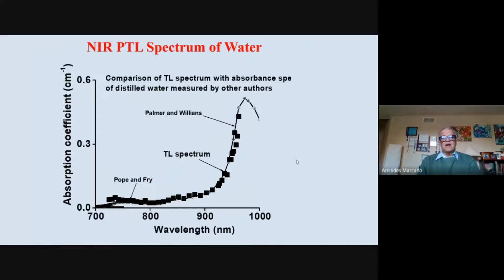You can also do a similar experiment using, for example, a femtosecond laser, what they call the mode-locked laser, which is a titanium sapphire laser, which is very common. People work with the femtosecond, but you can also work in CW regime. We compared the experiments in the infrared, taken from the TL spectrum, which are the squares, and the other points are from other people doing the experiments in transmission. Here the scattering is not important because you are in the infrared. You can see a very good coincidence in that region of the infrared. If you happen to have these kinds of lasers, you can do this spectroscopy right away.